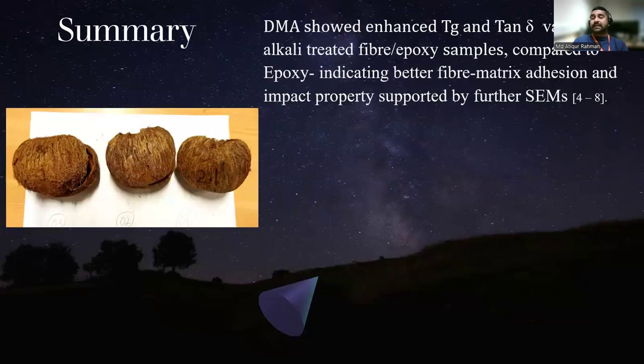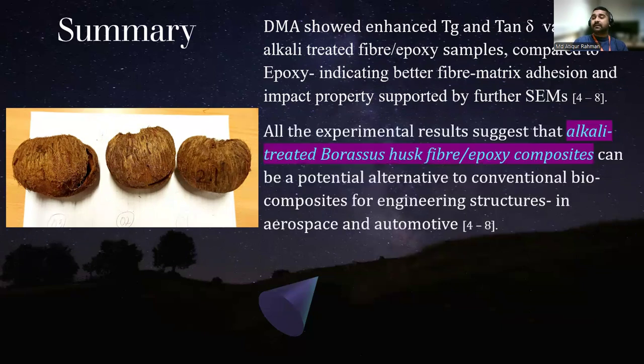And DMA showed the enhanced Tg value, glass transition value, and damping factor value for the alkali treated fibers compared to the raw epoxy and untreated one, indicating better fiber matrix adhesion and impact property, and that is supported by the SEM result. All the experimental results suggest that alkali treated Borassus husk fiber epoxy can be a potential alternative to conventional biocomposites for engineering structures, especially in aerospace and automotive. That was the part of my research.